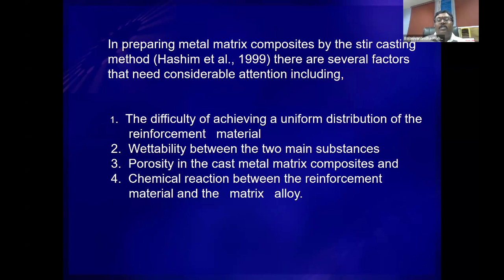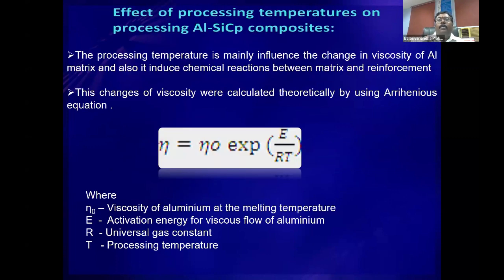But the main challenges in metal matrix composite production are four, I would say: difficulty of achieving uniform distribution of the reinforcement, then the porosity, the chemical reaction, then the wettability. See, the uniform distribution, for example, is controlled by the viscosity, and here we have a viscosity relationship, which is an inverse proportion. So the relationship between the viscosity and temperature is given here. It has an inverse proportion. That means when the melt temperature is high, the viscosity will be lower.